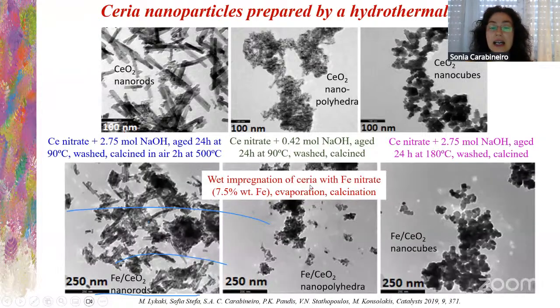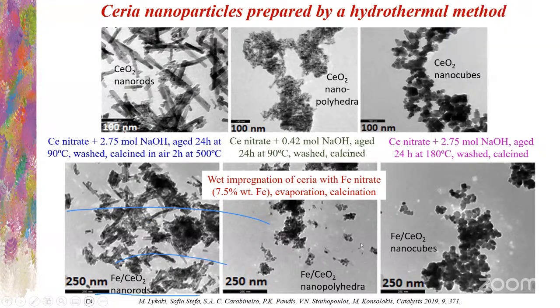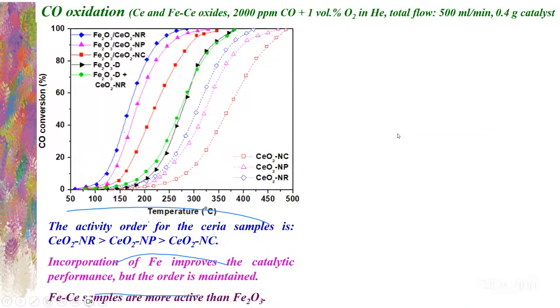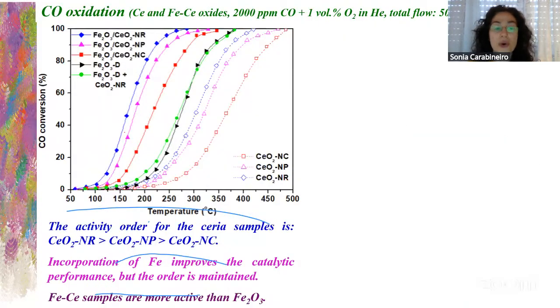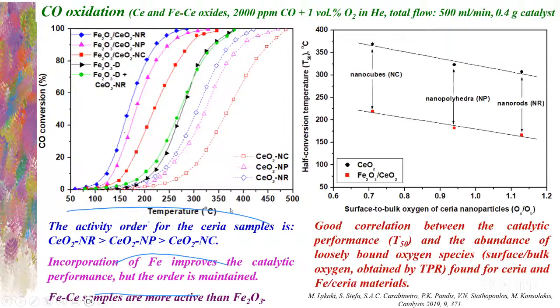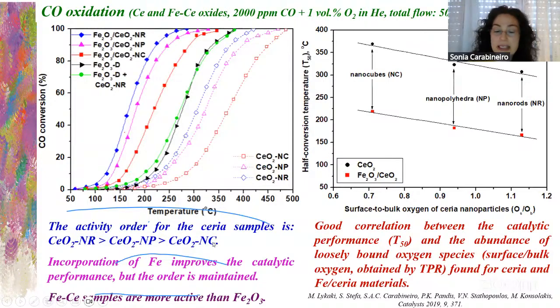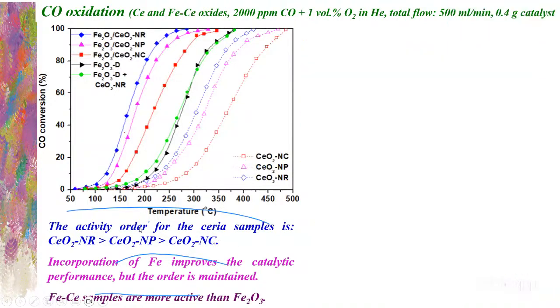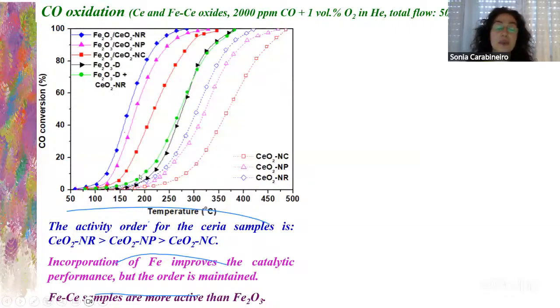And here we see if we impregnate it with iron nitrate, then you obtain iron on this support. So we obtain iron on cerium oxide. And if we compare these materials for CO oxidation, the activity order is nanorod is better than nanopolyeder, and cerium oxide nanocubes are the worst. Okay, and incorporation of iron improves the catalytic performance, but this order is maintained.